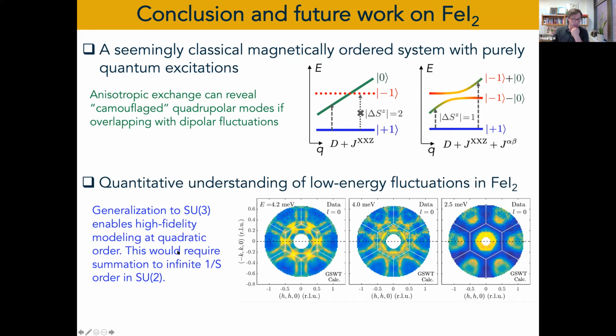And what's quite nice, at least what Christian tells me, is that if you wanted to do this with SU(2) spins, you would have to sum a lot of diagrams because you need to create this bond state perturbatively. You're summing 1/S terms in your Hamiltonian. But here, this SU(3) representation brings on equal footing the quadrupolar and the dipolar sector, and you can simply couple them. And at the end of the day, it looks almost a textbook example of a hybridization between two modes with different quantum numbers. But to get there, we had to develop all these techniques and also push the resolution of instruments and the crystals, etc.